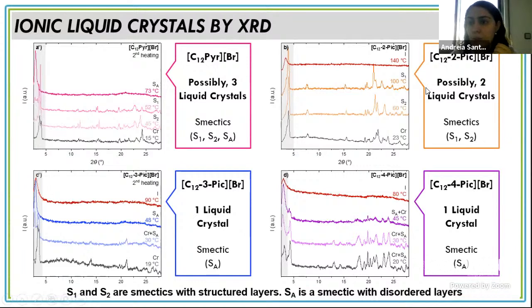For the case of C12 2-picolinium bromide, two different liquid crystals were detected, both smectic with structured layers. And for the case of C12 3-picolinium bromide and C12 4-picolinium bromide, only one liquid crystal was detected, and in both cases it is smectic A, which is smectic with disordered layers.